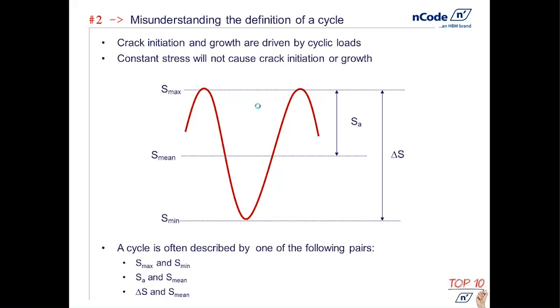We also know that constant stress will not cause crack initiation or crack growth. So what's really important is to be able to quantify a cycle — how big is this cycle? We can see on the graph we've got a very simple sine term. What we can say is that a cycle can be described as having a peak, followed by a valley and then returning to another peak. The shape of this particular curve is really not the most important thing.